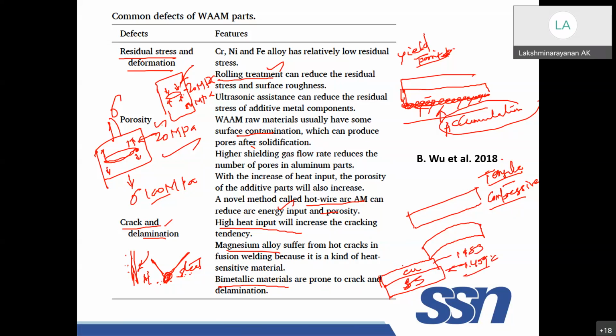The other problem is thermal conductivity. We all know this is a good conductor of heat and this is a very poor conductor of heat. So naturally there is differing thermal expansion. Everything is different, so there will usually be crack formation as well as delamination. This will not adhere to this. If the melting is not proper, it will not adhere to the stainless steel. So these are some of the common defects.